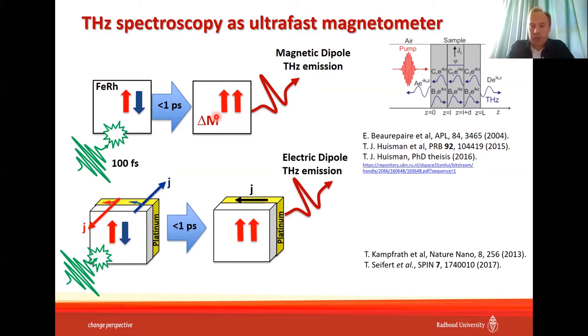Then there is another approach suggested by Tobias Kampfrath, that if you put platinum next to the metallic magnet, and if you change magnetization in the metallic magnet, upon transition from antiferromagnetic state to ferromagnetic state, you change the energy potential for spin up and spin down. So it would mean that the electrons with spin down will fly to platinum. So at least there would be gradients of the potential energy from iron rhodium to platinum. And electrons with the opposite spins will fly from platinum to iron rhodium, such that total charge current will be zero. So although total charge current is zero, the spin current is not zero.